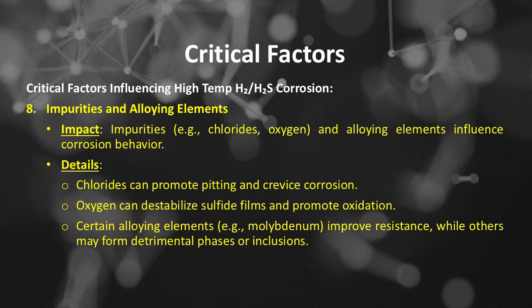Critical factors. Number 8 is impurities and alloying elements. The impurities and alloying elements impact: impurities, such as chlorides, oxygen, and alloying elements influence corrosion behavior. For details, chlorides can promote pitting and crevice corrosion, and oxygen can destabilize sulfide films and promote oxidation. Certain alloying elements, such as molybdenum, improve resistance, while others may form detrimental phases or inclusions.